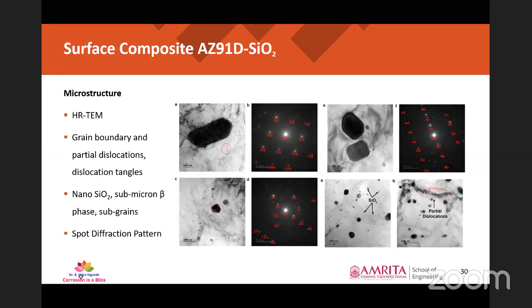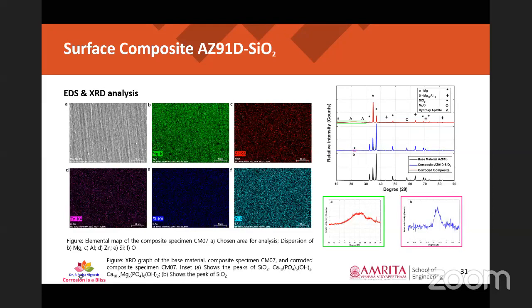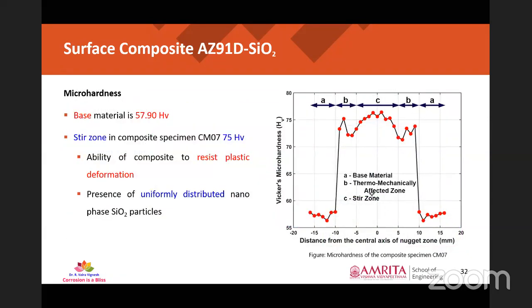In addition, we have confirmed the dispersion fashion through elemental mapping also. The elemental mapping confirms that silica, which is shown as blue colored images over here, is completely dispersed in the matrix, and SiO2, oxygen in the sense silica, and the individual map of oxygen also confirm that it is completely dispersed in the matrix. We have done XRD analysis to confirm the presence of silica. That also confirms that nanophase silica is present in the composite material. So we have confirmed the grain refinement through microstructural analysis, through a normal microscope, transmission electron microscope, and XRD analysis too.